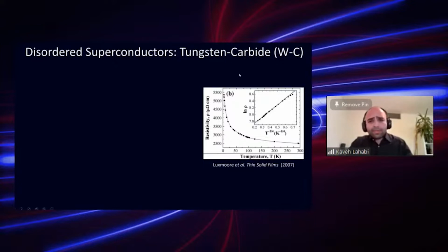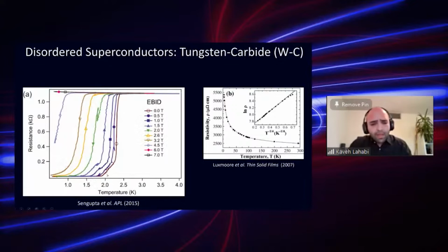In fact, when we started, there was one report where the authors succeeded in making superconducting tungsten carbide, but the transition temperature was about 2 Kelvin. And this was widely believed to be the limit of what you can do with this EBID. And 2 Kelvin is maybe a bit of an awkward temperature, because most cryostats usually go to at least 2.1 Kelvin. But we decided to give it a go anyway.